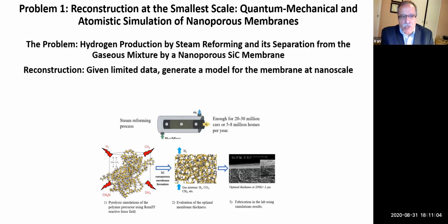Namely, they put methane and water at high temperature in a reactor at about 1,000 degrees, and then that produces hydrogen, and then you have to separate hydrogen from the other gases that are produced during the process. And for that separation, you need a membrane. Now, since this is a high temperature condition and also the reaction environment is highly reactive, the membrane should withstand high temperatures, but at the same time, it should be inert so that it won't react with other reaction products.